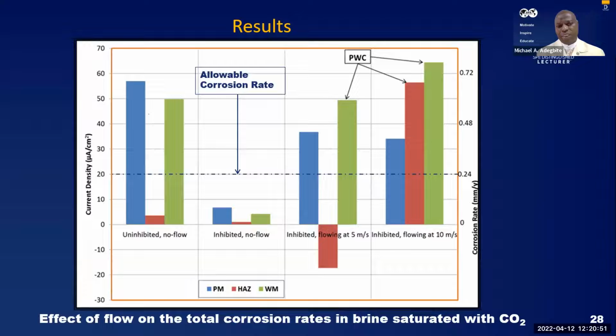And plotting, looking at the values and putting them together, we can see here the very first one. We can see in a no flow situation and uninhibited, that is without inhibitor, a typical corrosion rate. The weld metal is the green, the heat affected zone is red, and the parent metal is the blue. So without flow, that is in a storage system, we can have what we refer to as preferential weld corrosion.